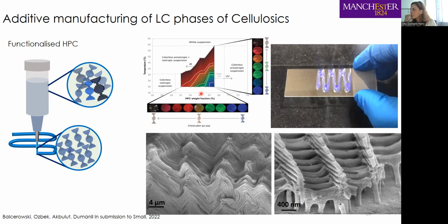But what we were very interested in was that we didn't have any angular dependency, and the reason for that reduction of the angular dependency is somewhat similar to morpho butterfly coloration, which suppresses the angular dependence by providing these complex wrinkles or pine tree kind of triangular structural formation as well.